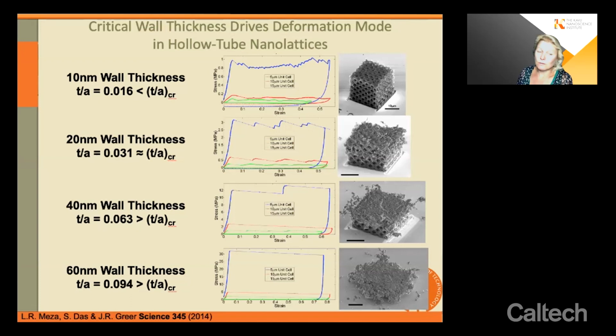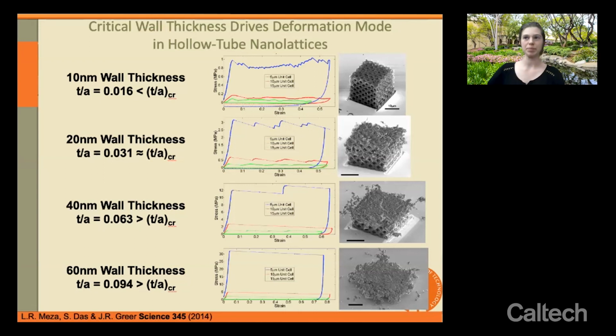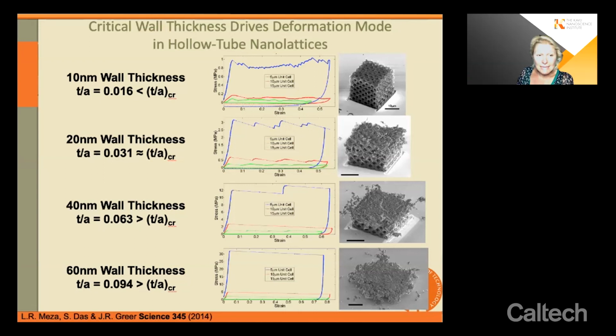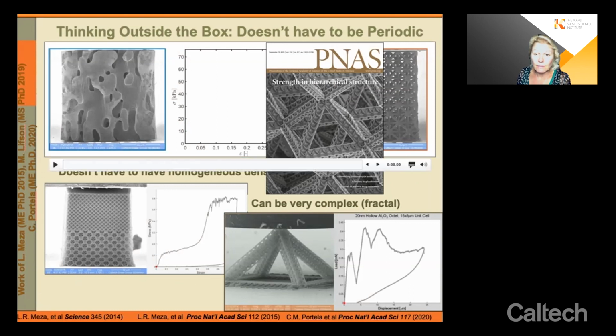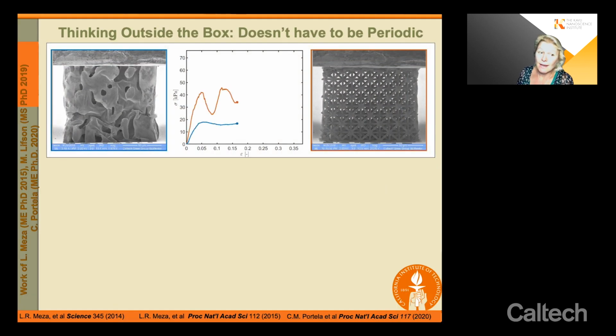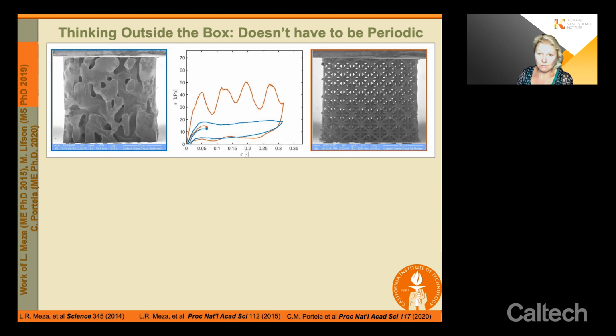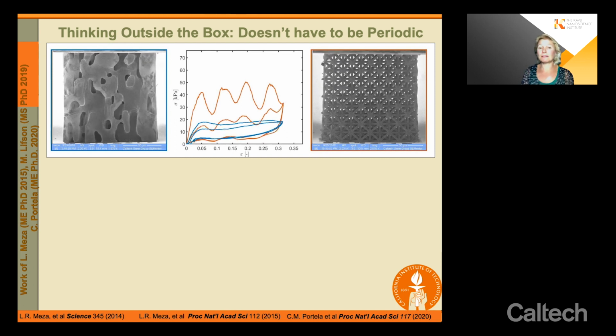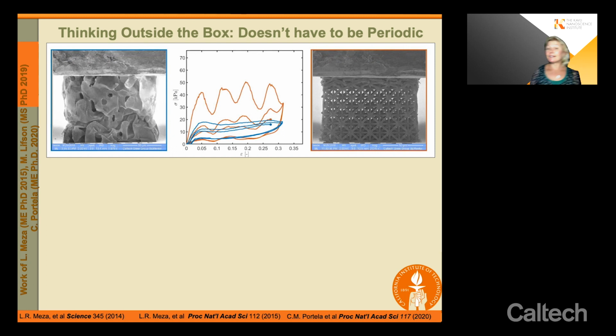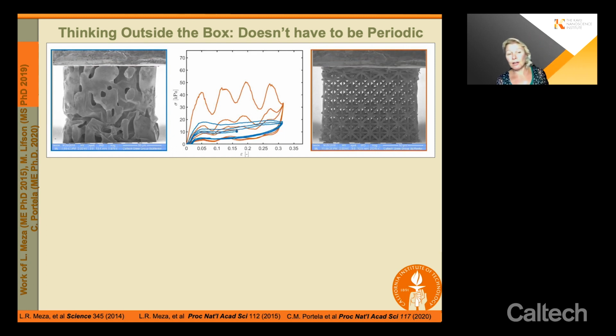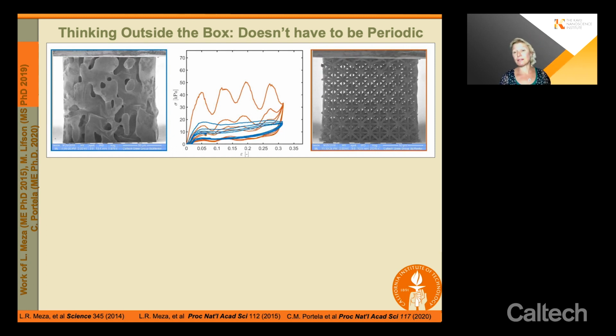Yeah, which ones though? The hollow ones, I guess, let's categorize them. Yeah, the hollow ones. It doesn't appear to be dependent on the complexity of the stress state. And so this is what I tried to demonstrate here. These stress states are very complex, as well as the geometries. They're inhomogeneous, and they appear to be not susceptible, at least their energy storage capacity doesn't seem to be a function of either the strain rate or the complexity of the stress state.